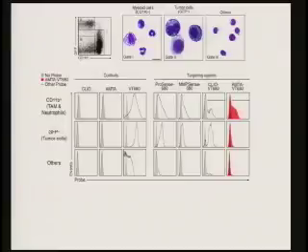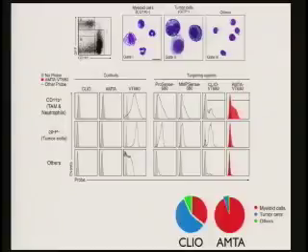So the experiments that we did is we started out with GFP cancer models, a number of different GFP cancer models, injected these nanomaterials, took the cells out, did extensive FACS analysis, and to make a long story short, this is our starting material. When injected intravenously, more than half of this compound actually ends up in tumor cells by itself. And remember, this is just a dextran-coated nanoparticle.